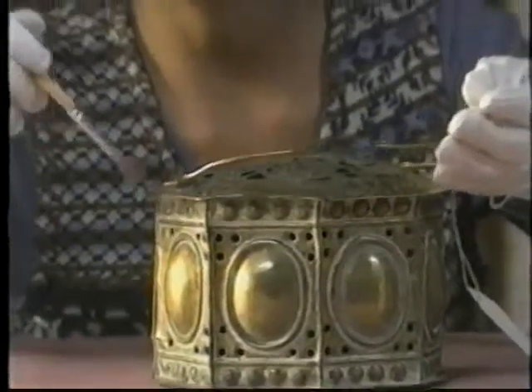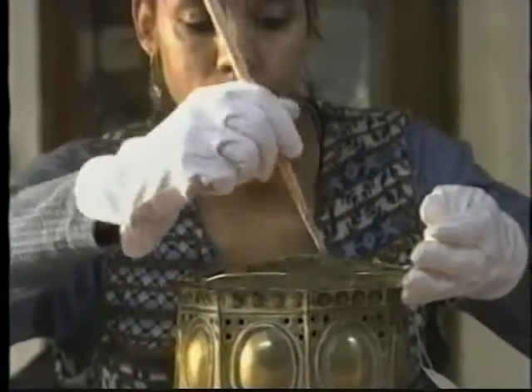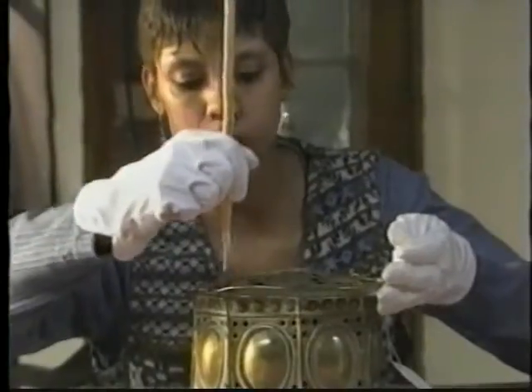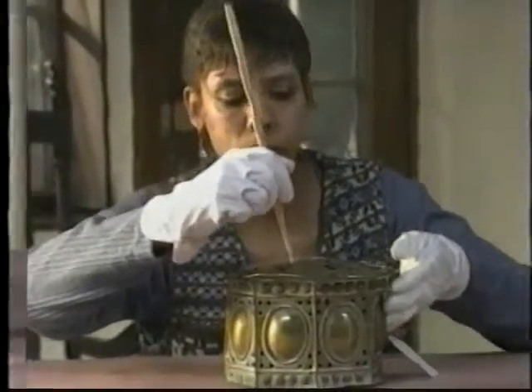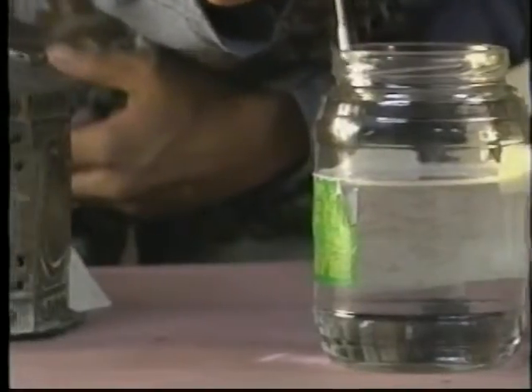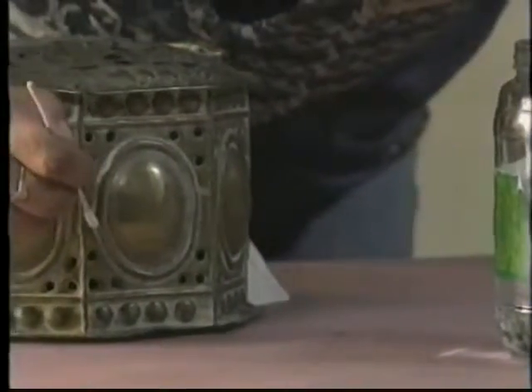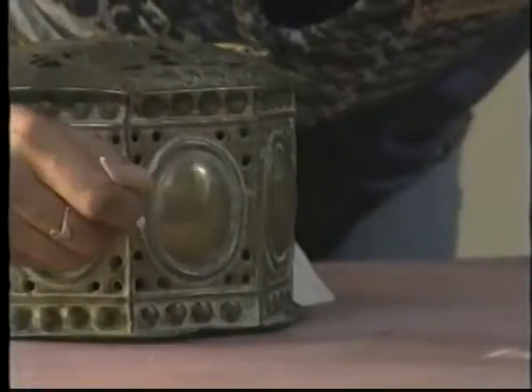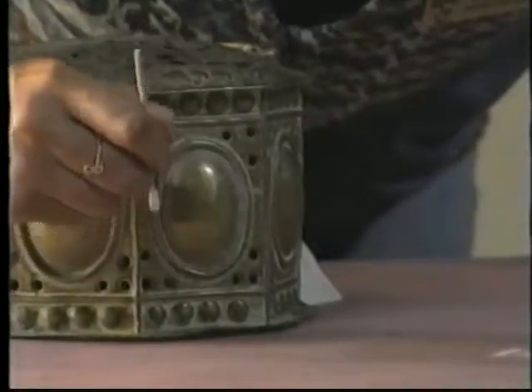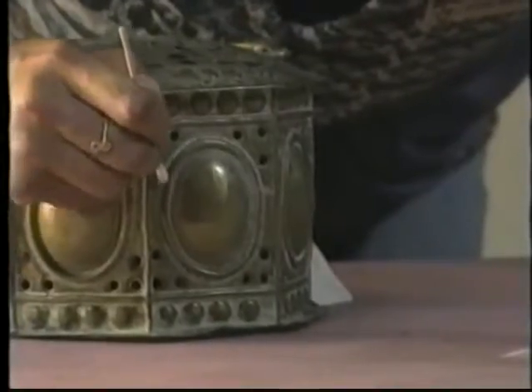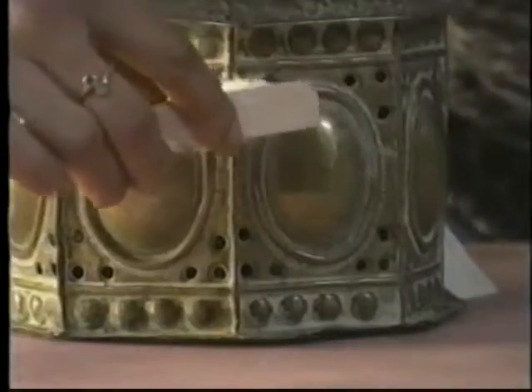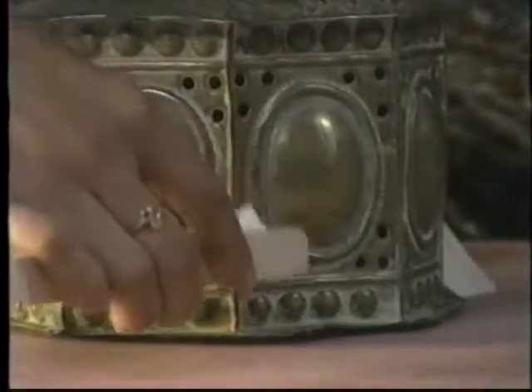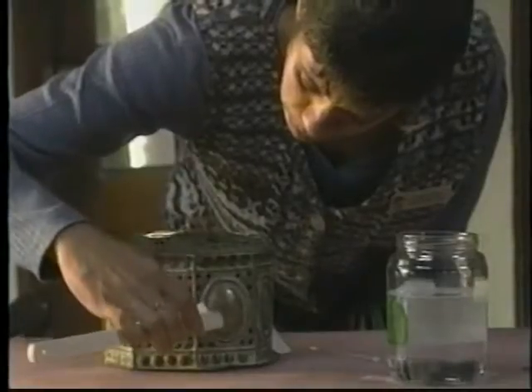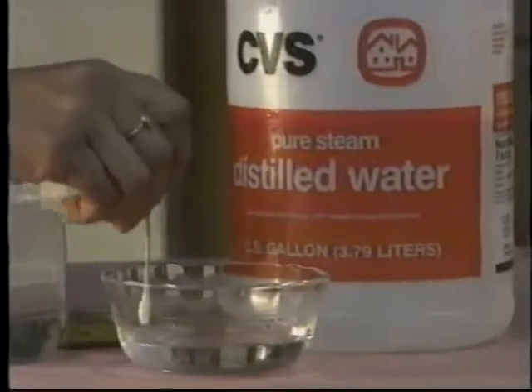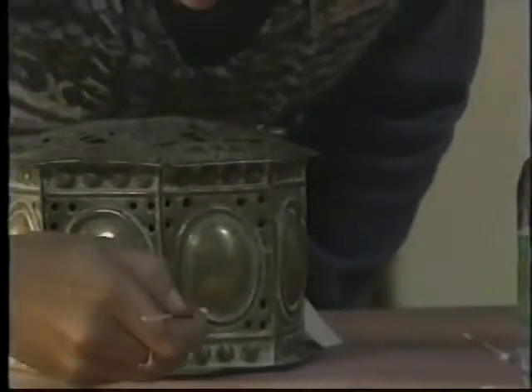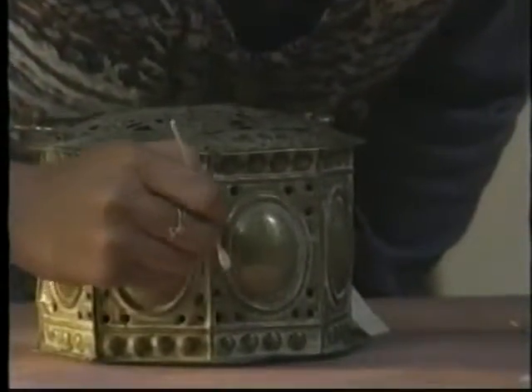Start by cleaning the object as you would in routine cleaning, brushing lightly with a soft brush or camel's hair brush. To remove old polish residue, make a very dilute solution of a few drops of detergent in distilled or deionized water. Clean with cotton moistened with the solution. Wait a few moments to allow dirt to loosen. You may free embedded material by agitating very carefully with a soft brush. Rinse thoroughly with clean distilled water. If iron has been used to strengthen the rim, do not use water in this area.